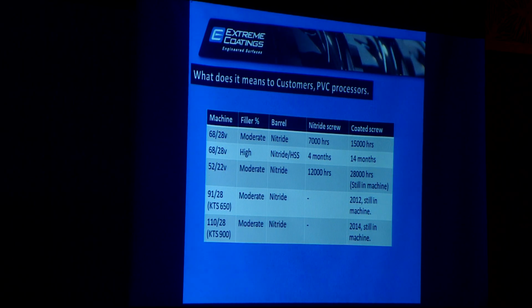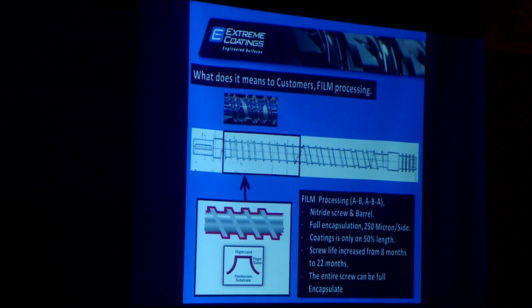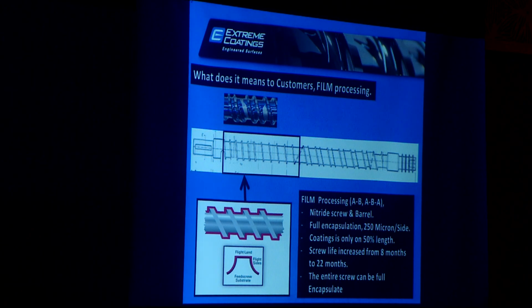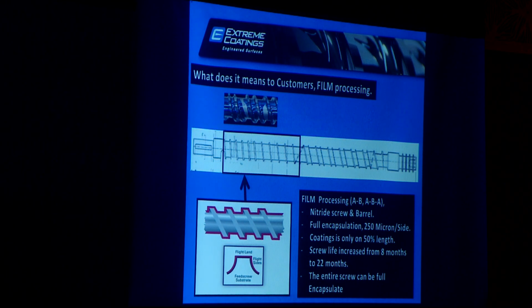In one case where the customer was having a very high percentage of calcium carbonate, the screw lasted only 4 months. With coating, it is lasting for 14 months. Same thing with the film processor also. If you are using a groove fit system, another advantage with the coating is that you can use the coating only on the required area. It's not necessary that you have to protect the entire screw. Like in this film extrusion line, LDPE, LLDPE or HDPE does not wear a lot. It's just the groove fit which creates pressure and wears out your screw. So we can put coating only on that pocket area, only 4-5 flights, and the screw will have a wonderful life.